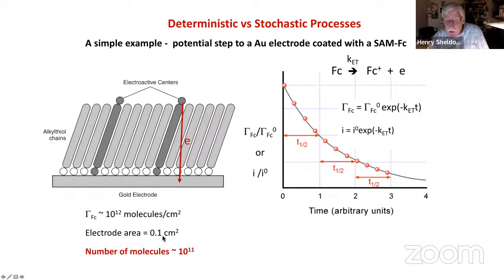They used a macroscopic electrode, 1/10 of a square centimeter. So the number of electroactive molecules on the surface is about 10 to the 11th. That's a huge number of molecules. So when you do this potential step experiment, the current decays exponentially. This is a first order process. The concentration of ferrocene that hasn't reacted decays exponentially.